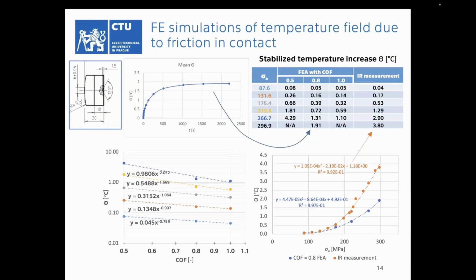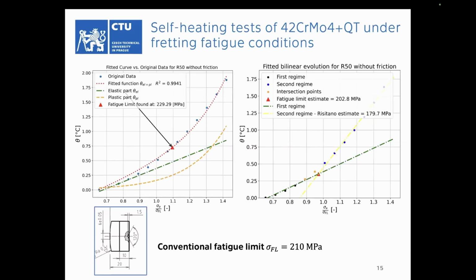So we have done this parametric analysis. You can see, for instance, that for coefficient of friction 0.5, the analyzed temperatures are higher than the measured ones. So finally, we decided to take, for illustration, data for 0.8, subtracted them from the measured temperatures to get a new self-heating curve. And if we reanalyze it by the methods that we used previously, we get this estimate of fatigue limit. We can see that for these single surface pads, the prediction is even slightly worse. In this case, if we apply Luong's method, there's, I think, no change.